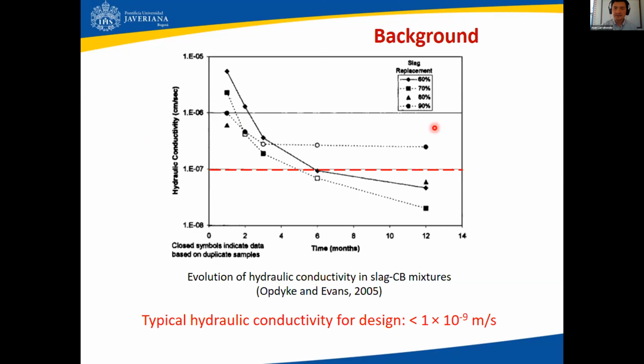So what you're looking at here is 4 curves with different slag replacements. Granulated ground blast furnace slag is, of course, as you know, a replacement cementitious material in these mixes. And normally the replacement percentage is in the order of 80%. And as you know, slag is a byproduct of the iron production industry. So in a way, we are reusing waste material in these types of processes because slag has cementitious properties itself.